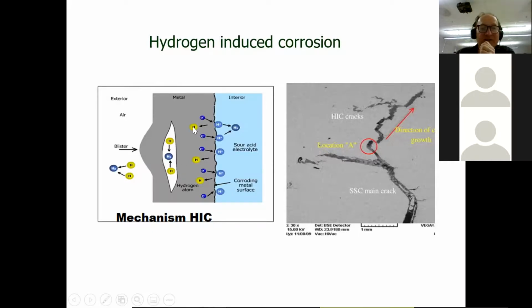And here you can see hydrogen in the, so here's the interior of the material, here's the exterior, got air. Here we got some kind of electrolyte. It says sour acid electrolyte. Don't worry about the word sour. That means it's got hydrogen sulfide in it, to be precise. But the point is it's acidic, so we have plenty of hydrogen ions around, and therefore the hydrogen gets inside the metal, and it can form a blister, because sometimes the hydrogen reacts inside, so you don't necessarily have to have a crack in this case. Hydrogen-induced corrosion doesn't necessarily mean you have to have a crack on the surface, because the hydrogen can diffuse through the metal, and in doing so react with it, especially if it's magnesium.